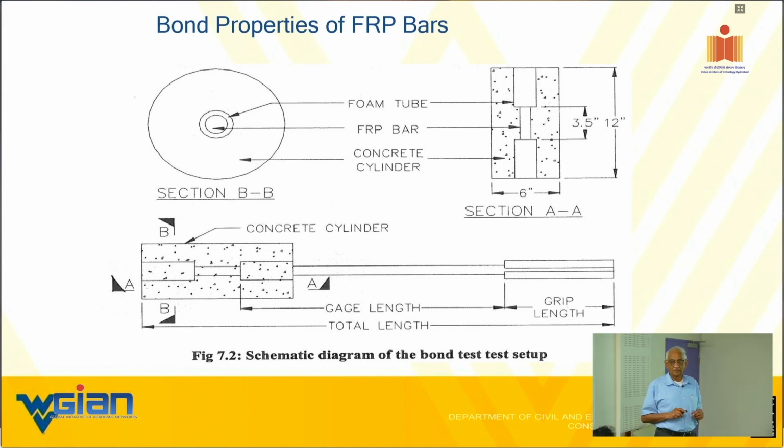And you also get an optimal resistance to pull force when you have between this 40, 50, 60 mils, divide that by 1000. So if you can keep that, whoever is going to run your shop should be made aware of these simple things, or else you get your results falling all over the map.